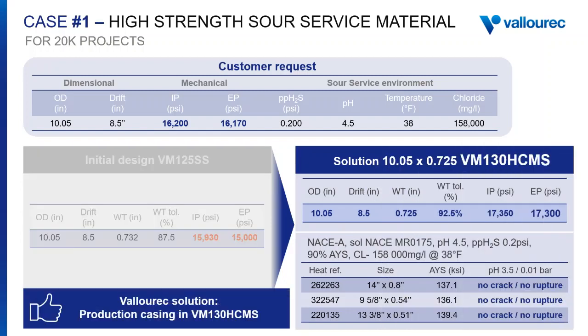As a solution, we were able to offer the VM130 HCMS, a mild sour grade with 130 ksi in combination with high collapse properties. This product not only allowed to keep the original design, but also to increase their safety margins, all while covering the corrosion resistance needed by the customer. For this case, we launched 3 fit-for-purpose NACE A corrosion tests in our laboratories in France, simulating the operation conditions. All NACE A tests passed, showing no crack and no rupture, proving that the grade was suitable for this condition.